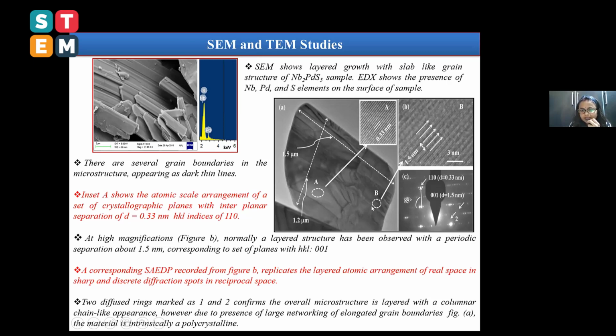And here you can see from this region B, the interplanar spacing is 1.5 nanometer, and this is the SAED pattern from this figure, from this region B. It confirms that there are two diffused rings, which confirms the overall microstructure is layered with a columnar chain-like appearance, however, due to the presence of elongated grain boundaries.